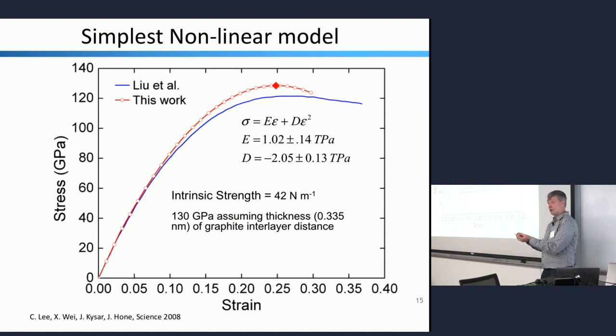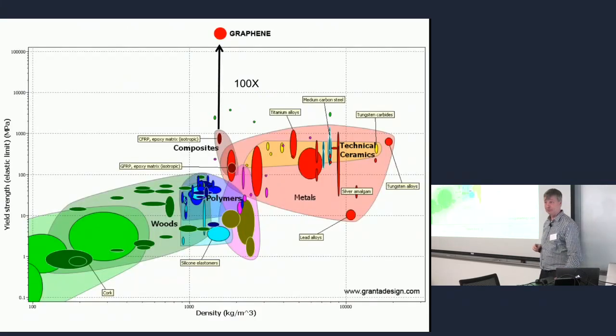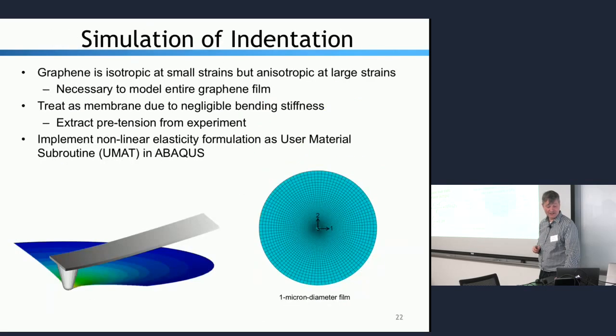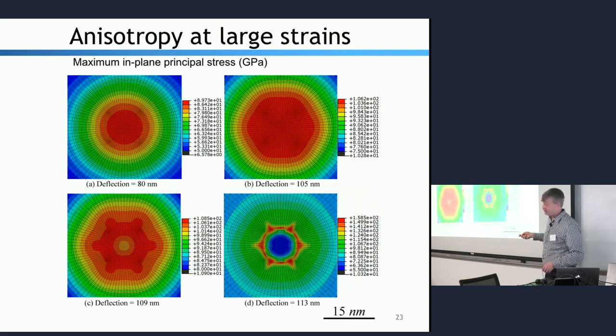And so the idea there is that locally you have some area of just a few nanometers at the point of the tip that is actually thermodynamically unstable. Right? If you were just pulling that, the stress strain curve is negative and it would be unstable. It would tear apart as you apply force. But you still have a ring of material that's on this side of the stress strain curve holding everything together, so the whole system as a whole is still stable. Right? And that's what we have here. So your unstable material is stabilized by this ring right here of material that's on the left side of that peak, right? So you get this small instability, and as soon as that grows and reaches the edge of the tip, that's your fracture point. Right? So a very small correction to our understanding of where fracture happens.